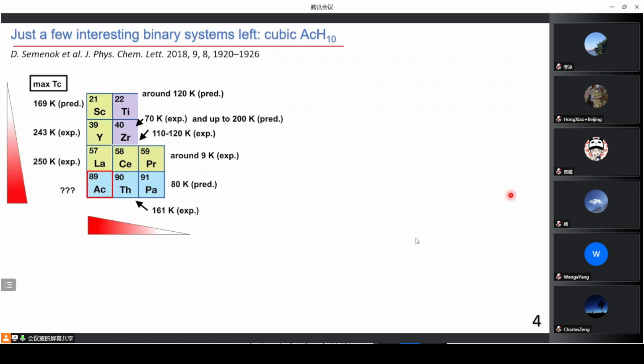And just a few interesting binary systems are left. One of them is cubic actinium H10. If you look at this part of the periodic table, we can compare the maximum predicted or experimentally found critical temperatures of superconductivity for polyhydrides, and we can see that when we move from up to down, from scandium to actinium, the maximum possible critical temperatures in these binary systems grow. Scandium H9 should have about 169 kelvins. Next is yttrium H9, 243, and next lanthanum H10, 250. So we expect to see higher TC for actinium H10 than was found for lanthanum H10.